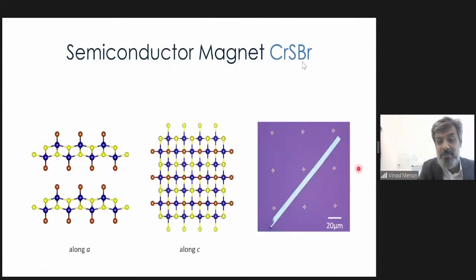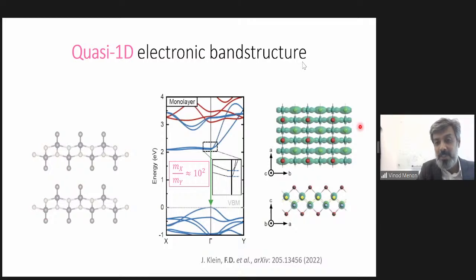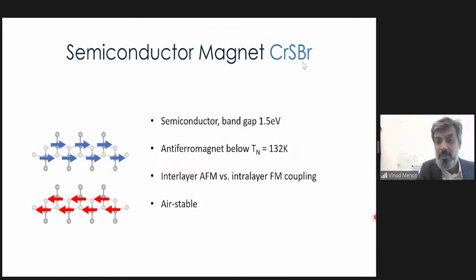And one of the materials we have recently started working with is chromium sulfur bromide, which is another van der Waals magnet. They're highly anisotropic. So if you exfoliate it, it becomes essentially a strip. And if you look at the band structure, the band structure is shown here. And this is taken from a recent collaboration of ours. So it's a semiconductor with a band gap of about 1.5 eV. So it's not a correlated material like I talked about earlier. It's an anti-ferromagnet below 130 Kelvin.